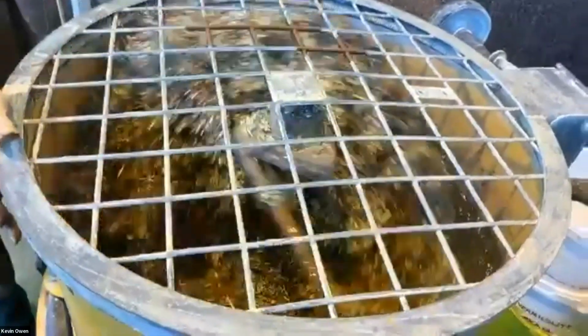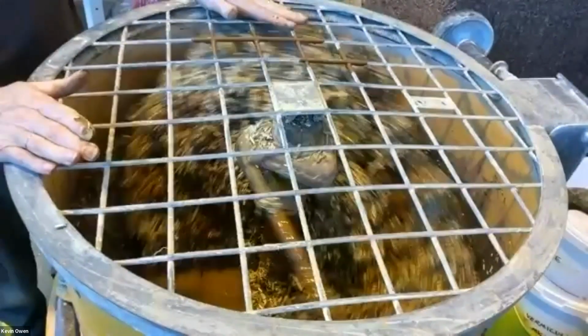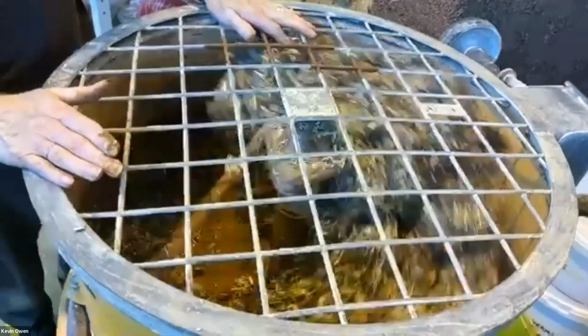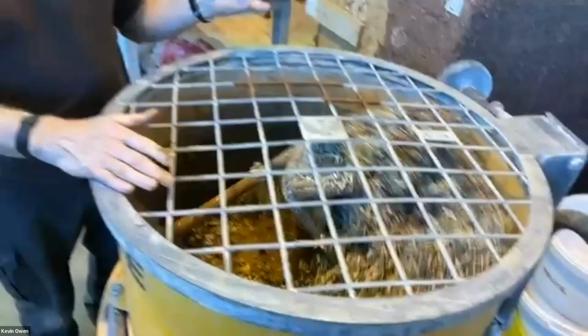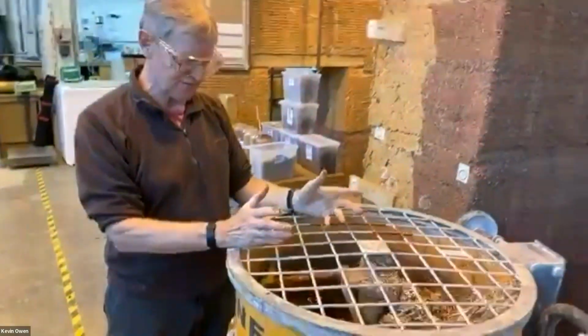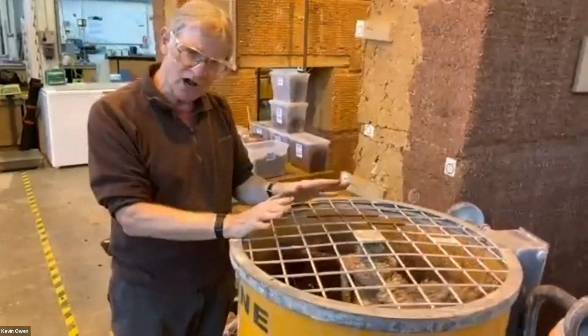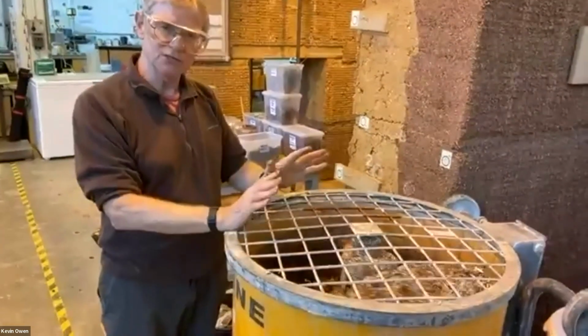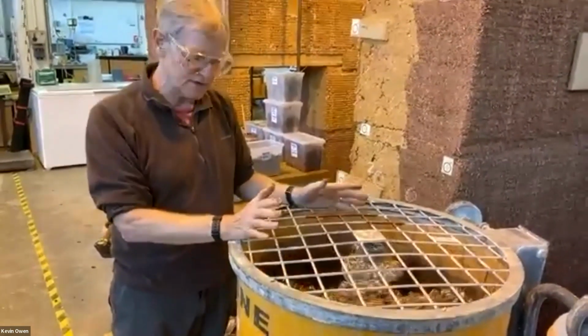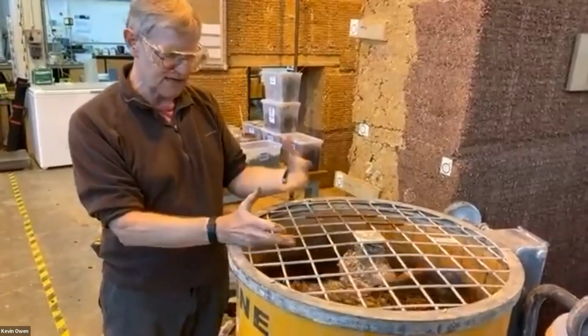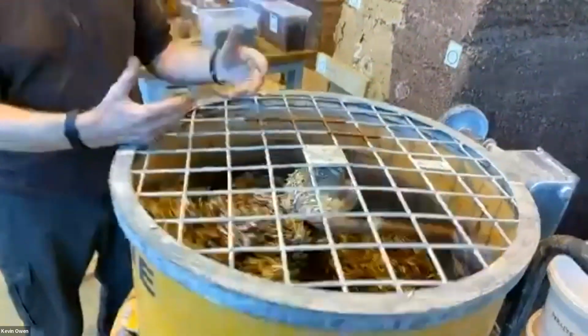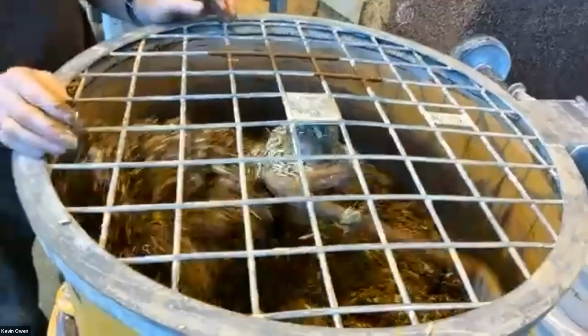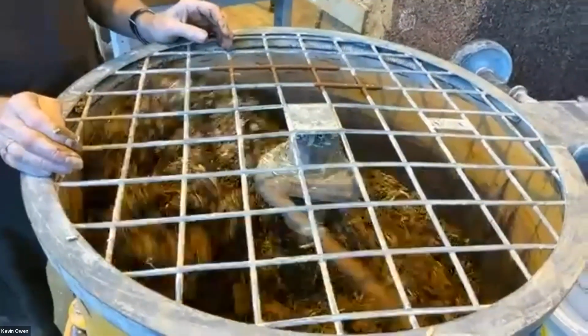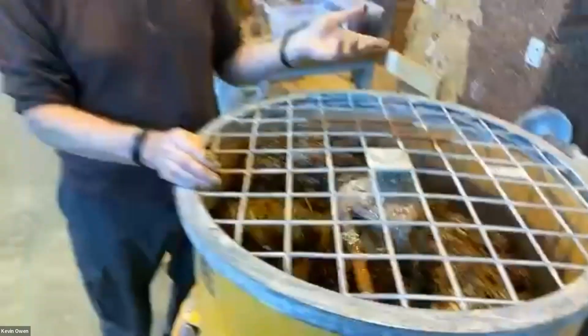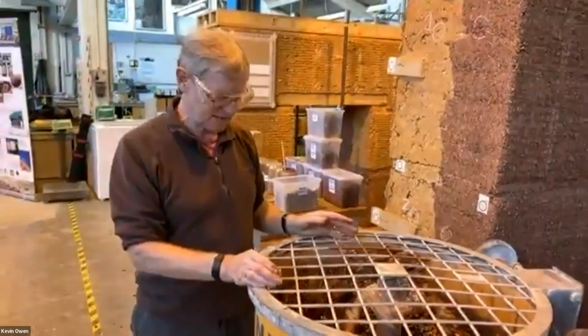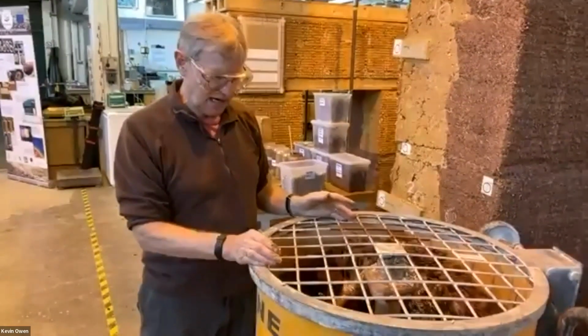That will now mix for a few minutes. It's a fairly quick process where the slip is being absorbed by the shiv. To start with, it looks very shiny, and then after a few minutes, it goes dull, and it's at that point that we know that it's fully mixed. As you can see there, it's changing colour from that light colour to a more redder, darker. And we usually would leave that to mix for, say, 5-10 minutes, until it's fully mixed up. And then it's ready to use.